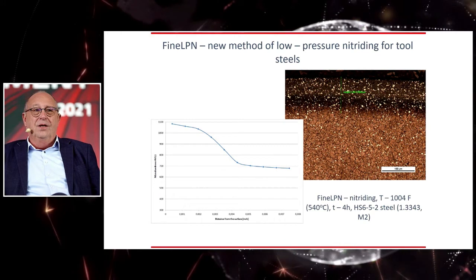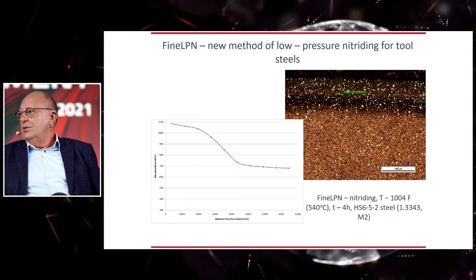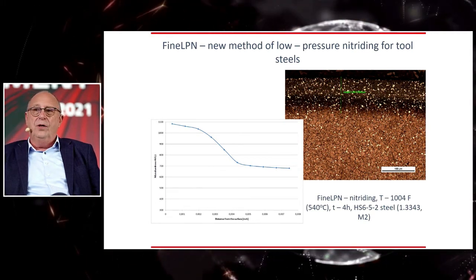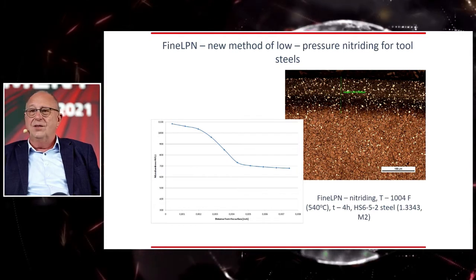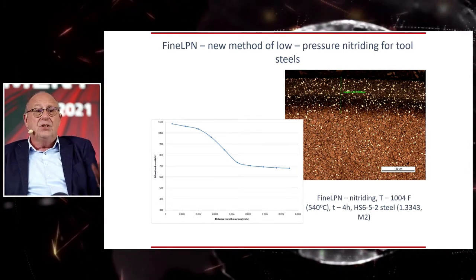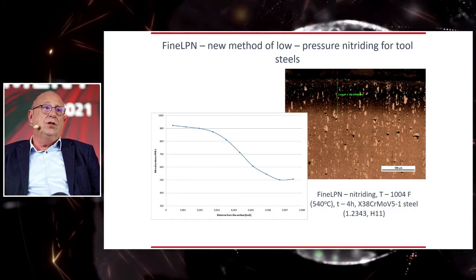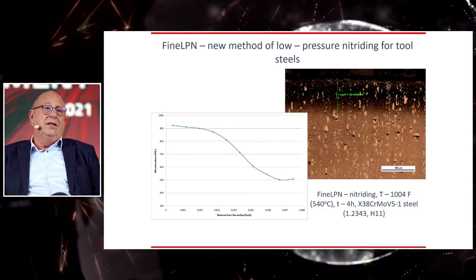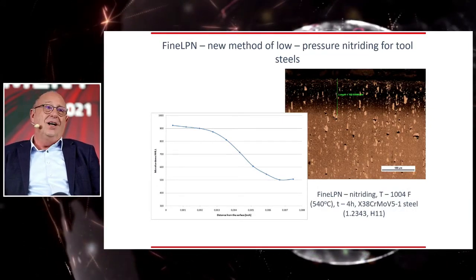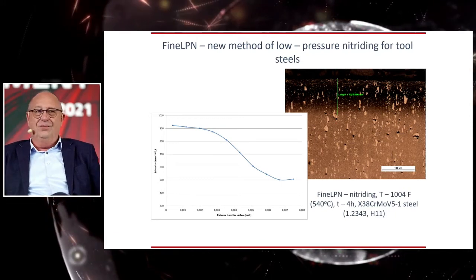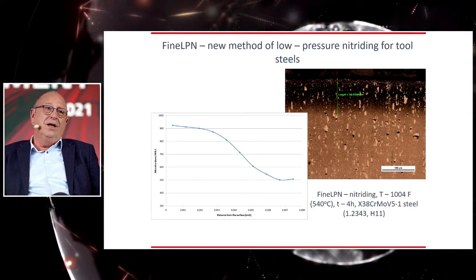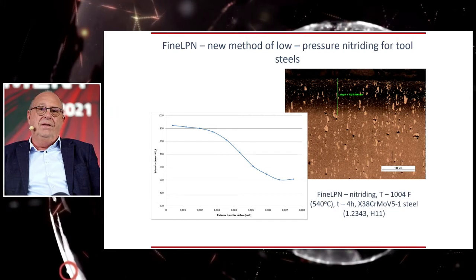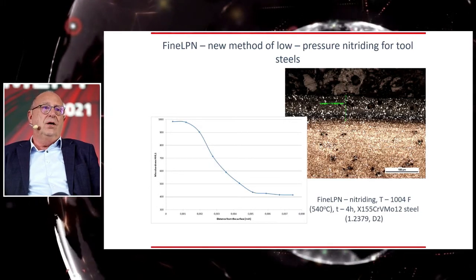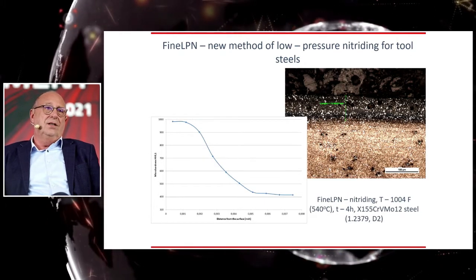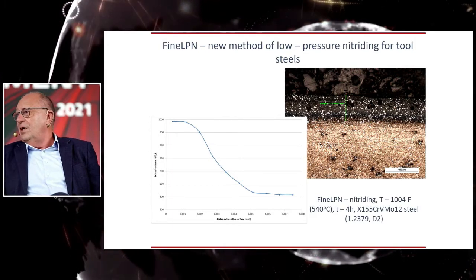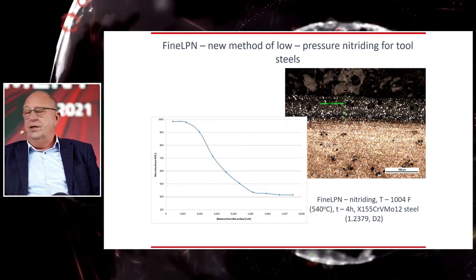So results were visible here. We are able to reach the proper microstructure. Only the dark layer without any traces of the nitrides on the surface on high-speed steels, like here, M2 steel, on the H11 steel, like here, and very nice the hardness profile obtained in this technology, and finally also on the D2 steel. No nitrides on the surface, only dark layer.